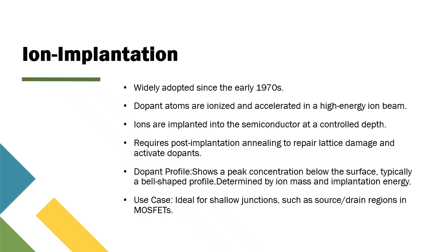However, this process causes some lattice damage, so a post-implantation annealing step is required to repair the crystal structure and activate the dopants. Unlike diffusion, the dopant profile here shows a peak concentration beneath the surface, often with a bell-shaped distribution. The depth spread of the profile is determined by the ion mass and implantation energy.